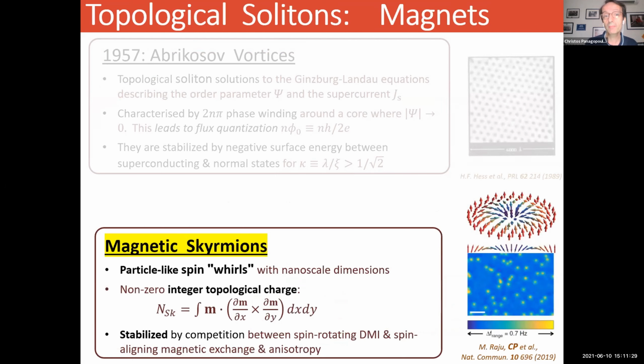Essentially, what this means in physics is that they are particle-like spin swirls with nanoscale dimensions, just a few nanometers wide. They have a non-zero integer topological charge, and they are stabilized by competition between the spin-rotating Dzyaloshinskii-Moriya interaction, which I will mention later, and spin-aligning magnetic exchange and anisotropy. And these are the forces that essentially stabilize these magnetic textures in a vortex form.